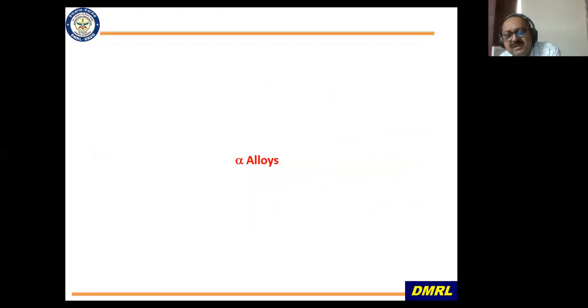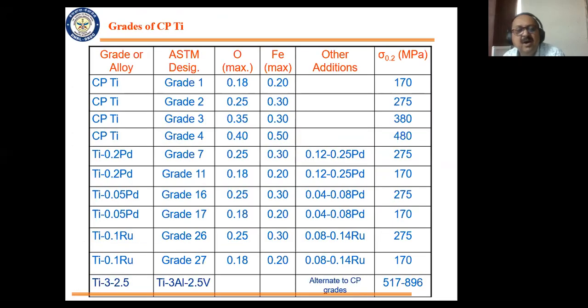So I will go on to first, alpha alloys. Now here are the commercial alpha alloys which are there. Several alpha alloys are shown here, starting with several grades of commercial purity. CP stands for commercial purity titanium, and you can see the only alloying element that you have is oxygen, and some amount of iron is put in because you want to control the grain size. Otherwise, these are single phase materials, difficult to control the grain size. Here I am showing you the yield strength.